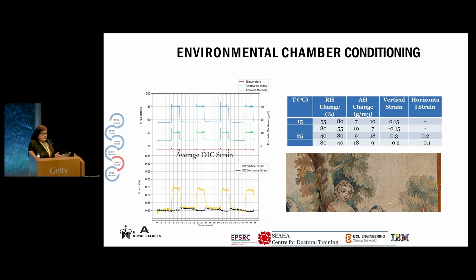just to note. So in the lower graph, we can see the strain calculations from the DIC with the vertical strain in yellow and the horizontal in black. These results indicate that strain changes match the changes in RH and absolute RH. The vertical strain is more affected by changes in moisture than the horizontal strain, potentially due to the increase of the tapestry's weight because of the exchange with the moisture.